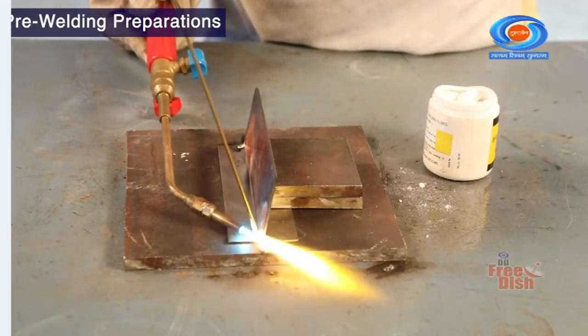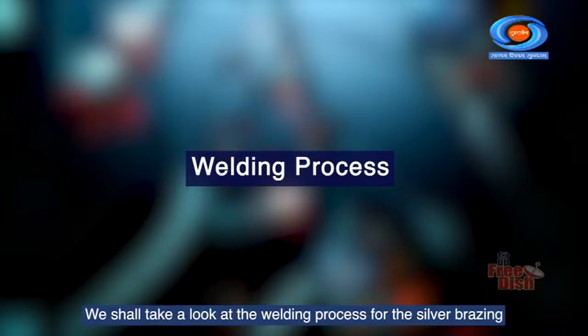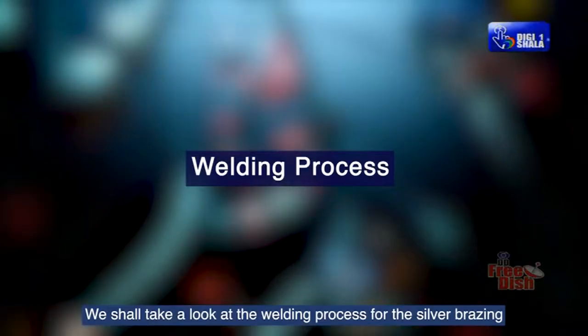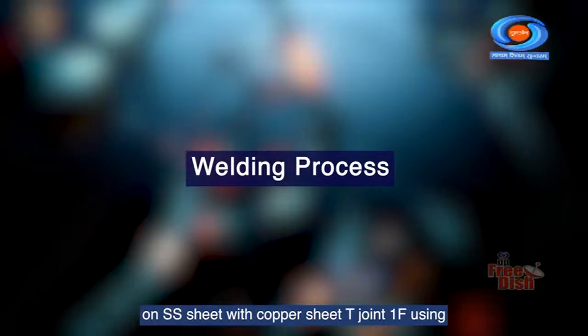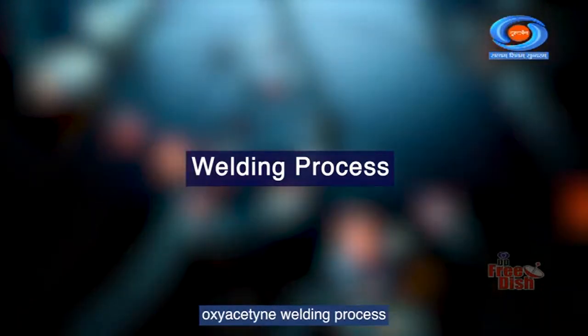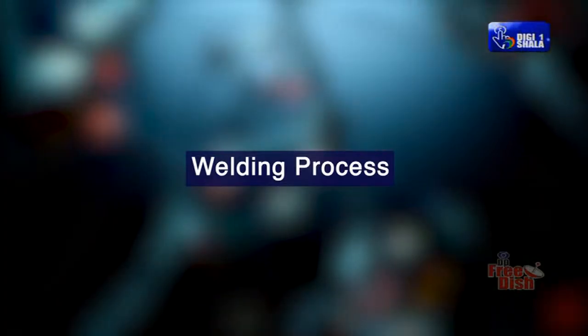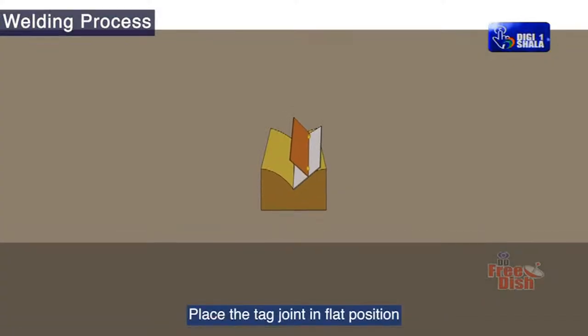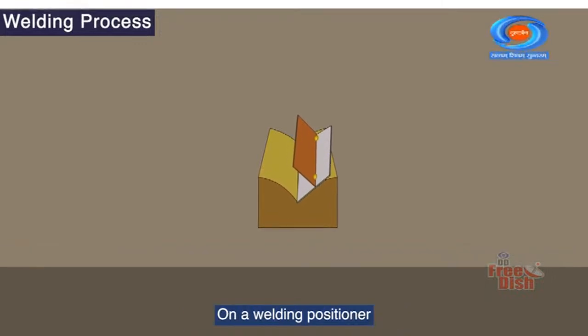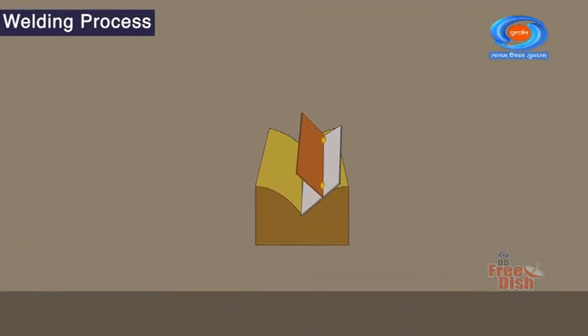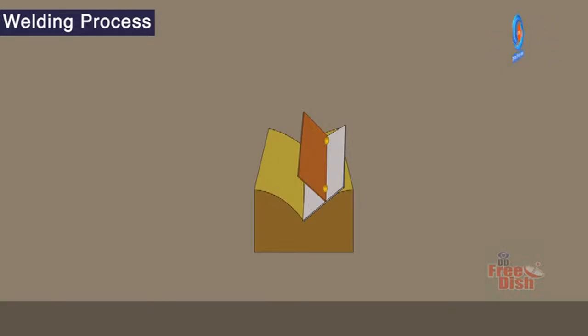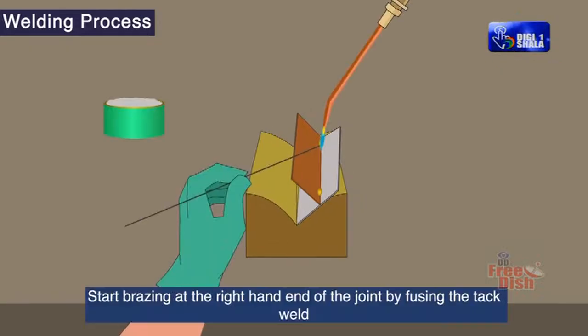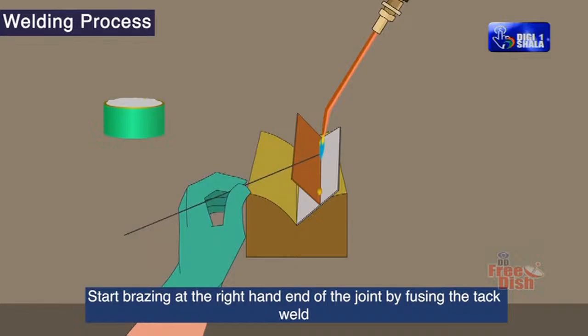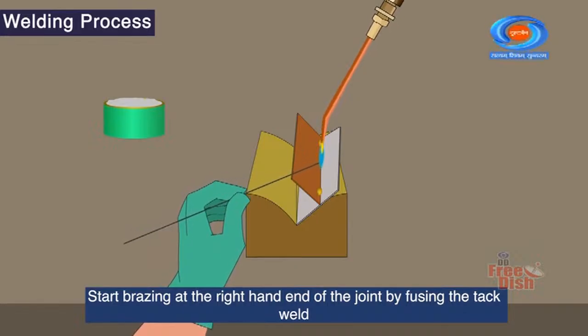We shall take a look at the welding process for the silver brazing on SS sheet with copper sheet T-joint 1F using oxyacetylene welding process. Place the tack joint in flat position on a welding positioner. Start brazing at the right hand end of the joint by fusing the tack weld.